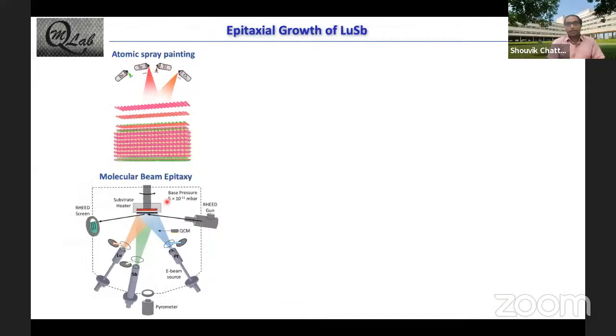So we went ahead and tried to see if we can create these materials in epitaxial thin film form. We use a technique called molecular beam epitaxy. To first order approximation, you can think of it as atomic spray painting, as I've shown here. What you have are very well calibrated effusion cells, or furnaces, if you will, which emit a very particular amount of molecular beams. We can calibrate them very well, and then they get deposited on a preheated substrate, and you can create your desired materials with atomic precision.